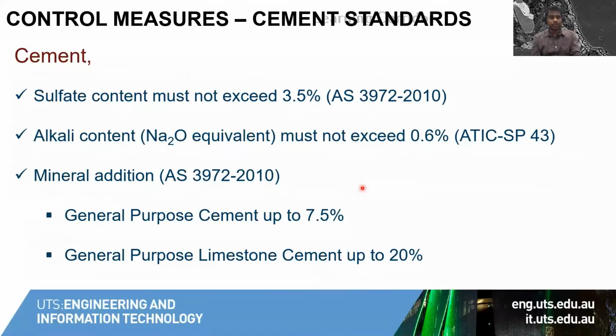Another way is to put restrictions on the cement sulfate and alkali content. In Australia, the sulfate content should not exceed 3.5%, and the total alkali content should not go beyond 0.6%. Cement standards also encourage the use of limestone as a mineral addition. Limestone substituted cements, in the long run, will produce other aluminoferrite phases which are non-expansive, for example monosulfate and monocarbonate in the systems. Those are non-expansive compared to ettringite. So limestone addition is encouraged.